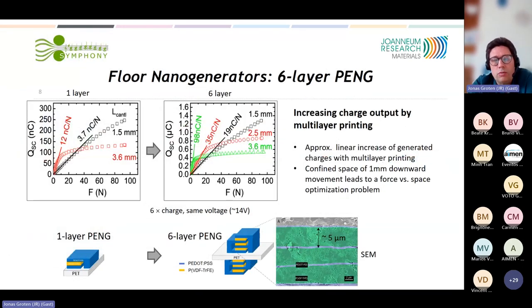Then finally, our goal was to increase the energy output. We achieved this by multi-layer stacking of the PVDF TFE on both sides of these cantilevers. And due to the space confinement, depending on the length of the cantilever, we can bend it more down or less down. And of course, longer cantilevers need less force to bend them down, but they will at a certain point hit the floor. So this gave an optimization problem for this floor